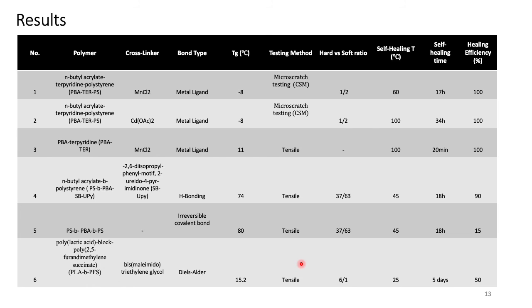And I think you can see here also different reactions. We have the metal ligand bond type, we have hydrogen bonding, irreversible covalent bonds, and Diels-Alder reactions. We can compare these two since they are the same materials. However, in the first one they used a cross-linker, and in the second one they didn't, and that actually affects the self-healing efficiency. As you can see here, the first one has 90% efficiency, and the other one has around 15% efficiency. At the same temperature, same hard versus soft ratio, and same test.